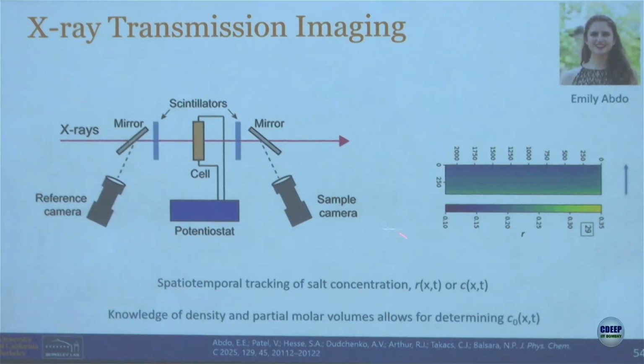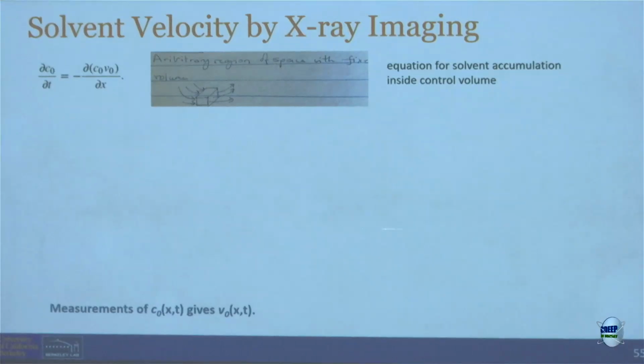If you know the concentration of salt, and you know the partial molar volumes, which we do, then you know the concentration of the solvent. Just basically 1 minus the C. And I was telling Emily, we should be able to get solvent velocity from this measurement. But how, I didn't know. And then she came up with this crazy idea that, you see, this is an equation that is basically a solvent